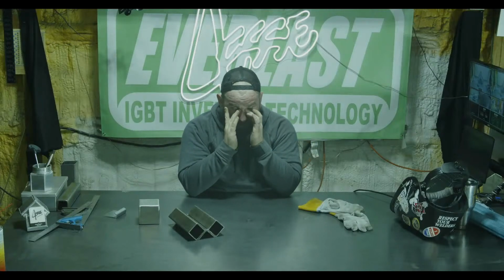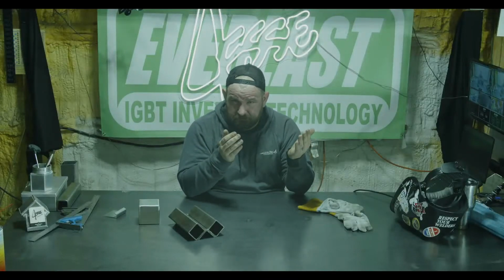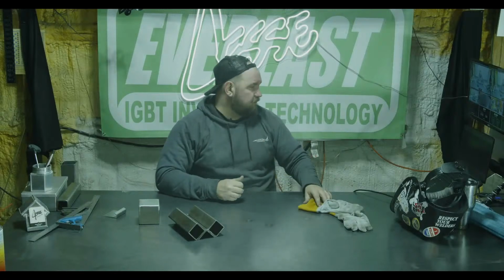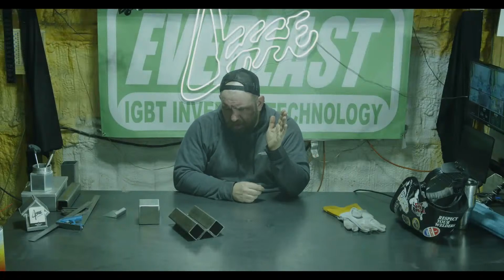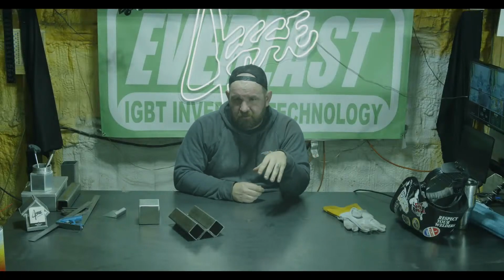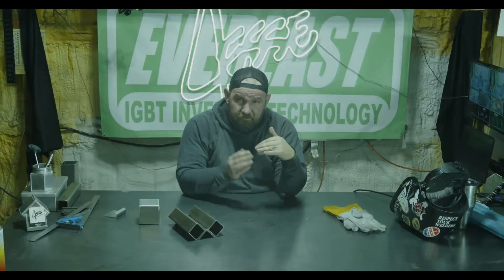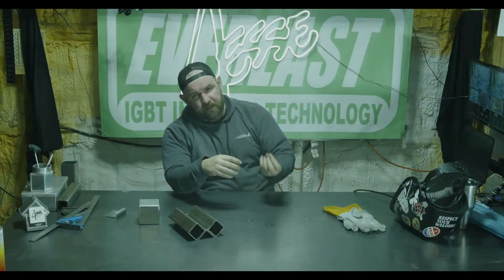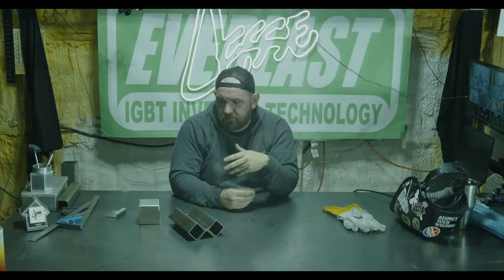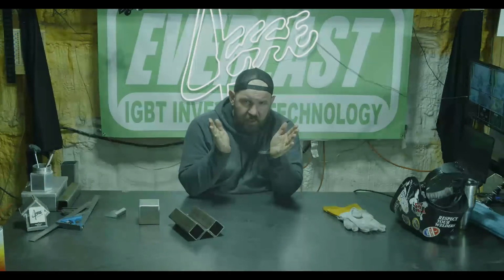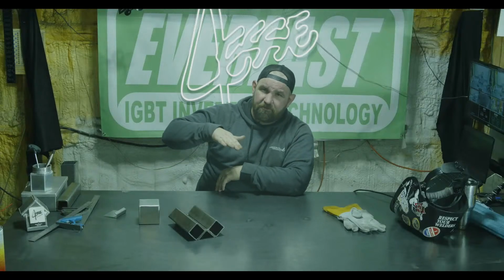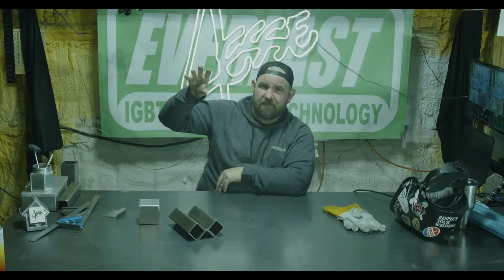What that does: back in the day, before AC, you welded aluminum on DC electrode negative, and you used helium. That's why it was called heliarc, because of the use of helium. DC aluminum runs extremely hot and extremely fast. It's a little bit of a dirty process, but you get a lot better penetration, because the penetration side of your AC waveform comes from that DC electrode negative side. The electrode positive is what lifts the oxide layer off the aluminum so you can get a cleaner weld. So the advanced AC pulse gives you the heat of your DC electrode negative with a little bit of cleaning from your standard AC waveform.